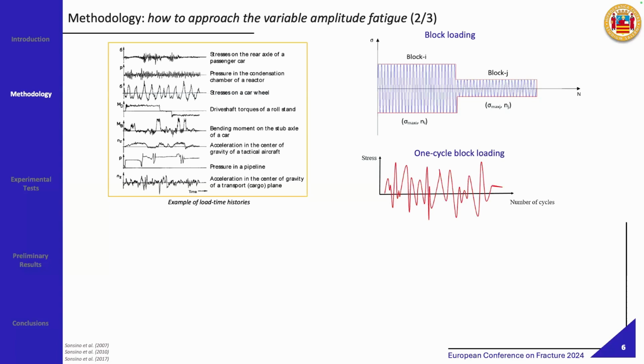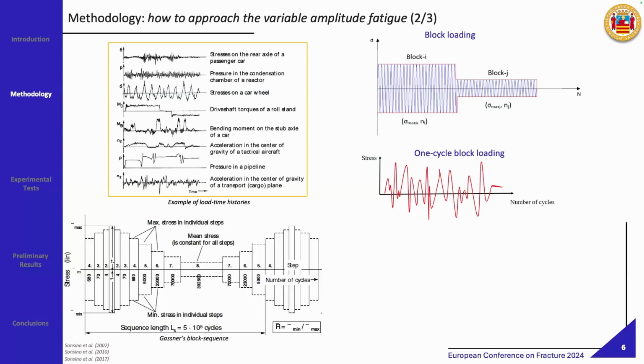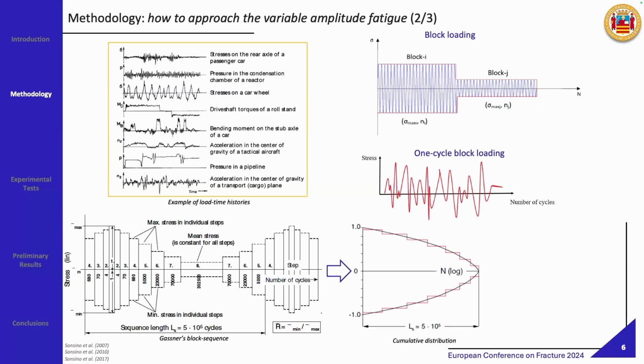Among the hundreds maybe of loading spectra that are available in literature, one of the first that was introduced was the 8-block Gassner sequence. Gassner was maybe the first scientist who tried to approach the variable amplitude fatigue issue, and I'm taking this just as an example. But we can say that starting from a variable amplitude fatigue loading, we can always extract a cumulative distribution of the load. This is just a way to represent our load based on the probability of exceeding a given stress amplitude.